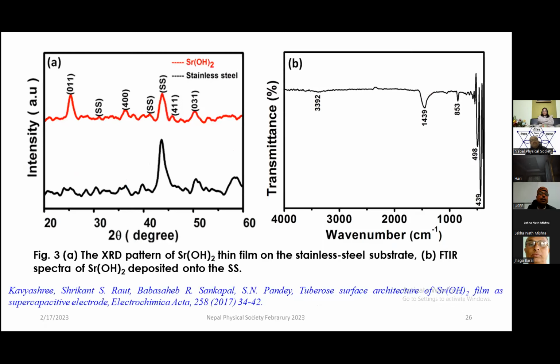So one can see here that the deposition has been completed, then the second thing is going to be characterization. Characterization is very important. So how can we characterize it? One can see the XRD pattern, and nowadays it is very easy to analyze it with the help of the JCPDS card. We have different SS peaks here, denoting the peak due to stainless steel, which is the substrate. I have taken stainless steel as the substrate, so small peaks are coming due to this. This is also due to the stainless steel. It is written here. And strontium hydroxide is having this peak.